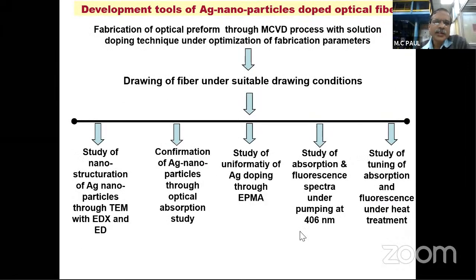This is the basic scheme: fabrication of the fiber by MCVD solution doping, drawing of the fiber, then study of metal nano characterization, TEM absorption study, electron probe microanalysis to study the distribution of silver nanoparticles along the diameter of the fiber, study of the absorption and fluorescence spectra under a 406 nanometer pump source, and study of the tuning property of the absorption and fluorescence under heat treatment.